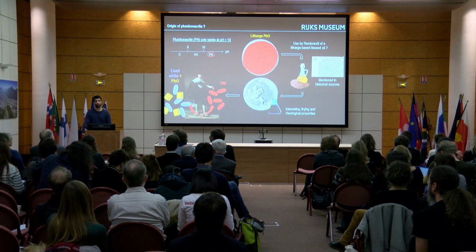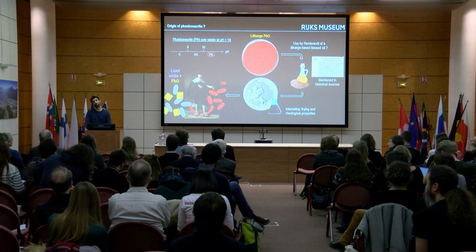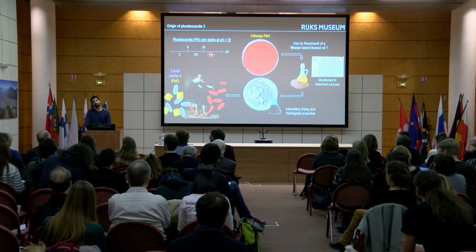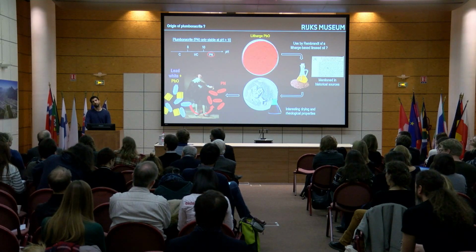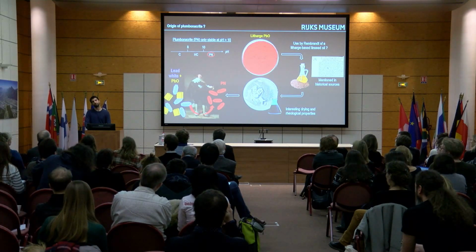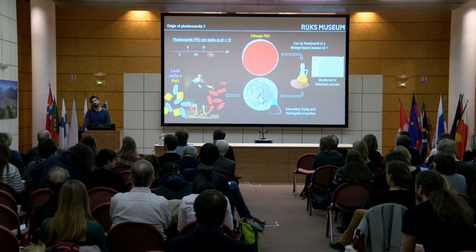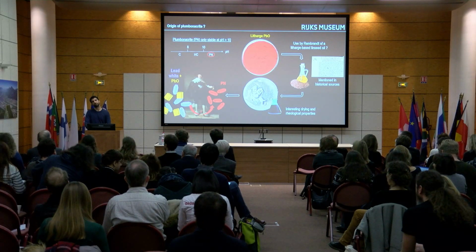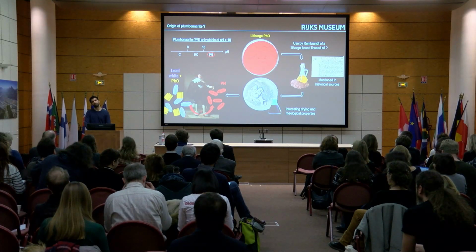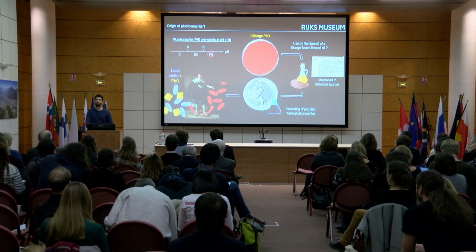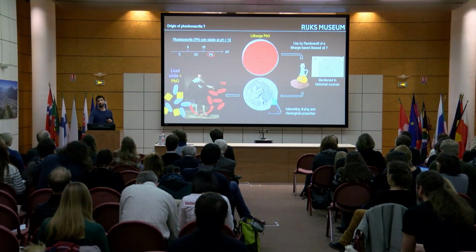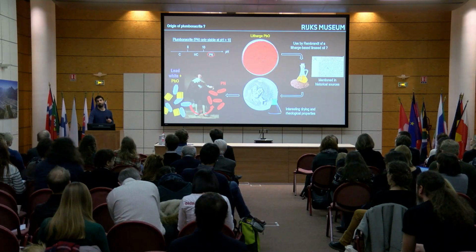One might ask the question of how the litharge was produced and whether it was a uniform phase. In Chinese art of the Song and Ming periods, we see litharge in coarse grains which has the consistency of a shell of lead oxide around a core of lead carbonate, and it affects the appearance. It gives it a brighter color. Depending on the way that the litharge was produced, in that case probably by roasting incompletely. Yeah. One might wonder whether the litharge used was really pure litharge.